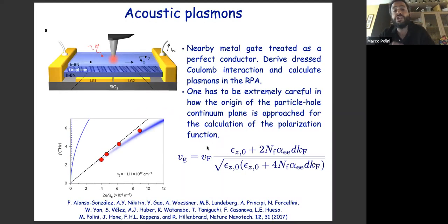You have to do a little bit of tip engineering, but from the fundamental physics point of view, you can do a very simple trick to make sure you have long-lived plasmons in the terahertz domain while working still with ordinary carrier densities in graphene. And the trick is to screen long-range Coulomb interactions by placing nearby gates. So by placing this LG1, LG2 split gate near graphene, let's say 5 nanometers, and then Frank and collaborators push this to 1 nanometer, 3 layers of boron nitride separation between the split